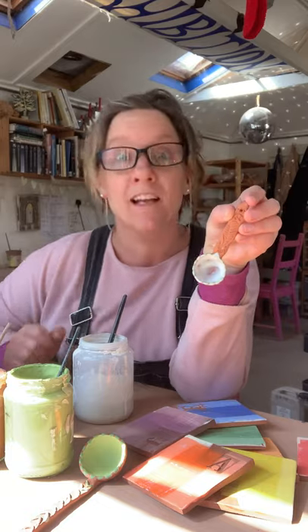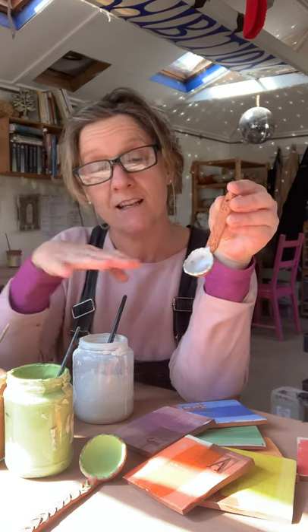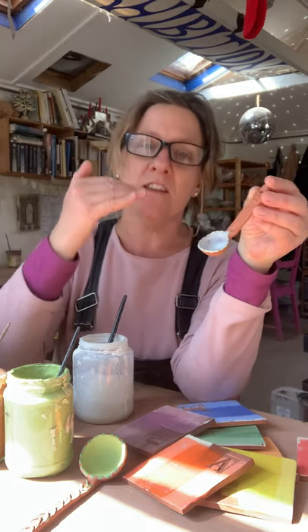It will go completely white — that's as it should be, don't worry. You're going to give it two nice thick even coats of this transparent glaze. Let the first coat dry — you'll know when it's dry because it will go to a chalky color, it just won't look wet anymore. Only then apply the second layer. Try to get it nice and even, particularly over really dark colors, because if you don't it can go a little bit milky over something like navy blue.